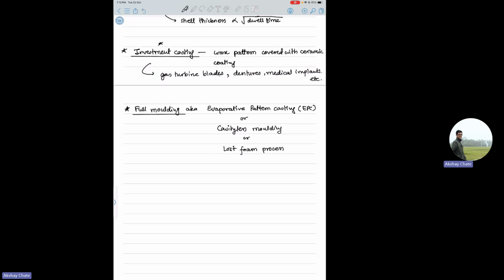And as the name suggests, you can look at the keyword evaporative. They use a pattern which is polystyrene foam or PVC. So you don't use wood or metal. You use a polymer like polystyrene foam, PVC, etc. to make the pattern. Then you don't remove the pattern. You just keep it inside and start pouring the liquid metal. This foam will have lower melting points, and even sublimation or boiling points. So when you pour liquid metal, they just evaporate.